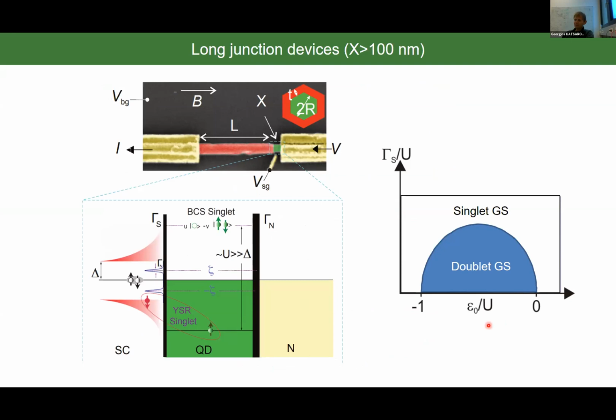So for example, if you have a quantum dot and you have an odd number of carriers, then depending on the ratio between gamma S and U, you can be either in the doublet ground state or in the singlet ground state. And in the particular case of our experiment, since U, which is the Coulomb energy, is much larger than the superconducting gap, our singlets are YSR singlets, about which Katharina Franke gave a very nice talk yesterday afternoon.